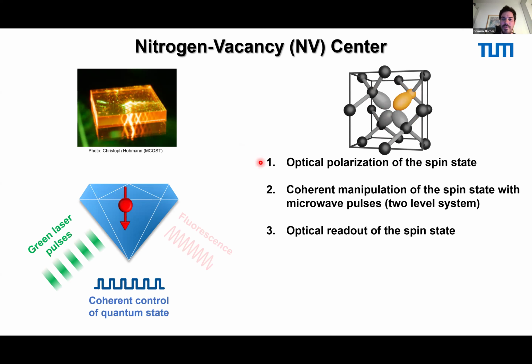And the question is, why is this defect in the diamond so important or so useful for us? Well, because it has three distinct properties. So first of all, we can optically polarize its spin state. So this defect here, you can think about as an electronic spin sitting in the diamond lattice. We have a very long coherence time of this electronic spin because it is kind of confined or protected from the environment by the diamond lattice. And we can do coherent manipulation at room temperature with microwave pulses. And very important, we can also use optics to read out the spin state of this defect, because depending on how the quantum state, the spin state of this defect is, we have a different intensity in fluorescence. Okay. And you see these three criteria define a fully functional qubit, again, importantly at room temperature, which is of course also important if we think about biological applications.